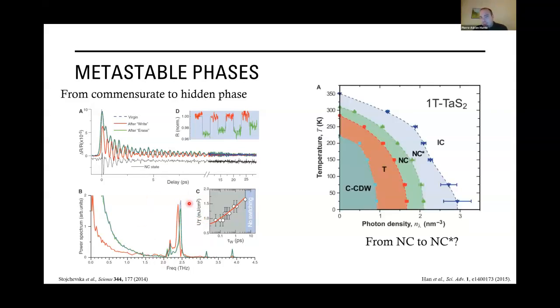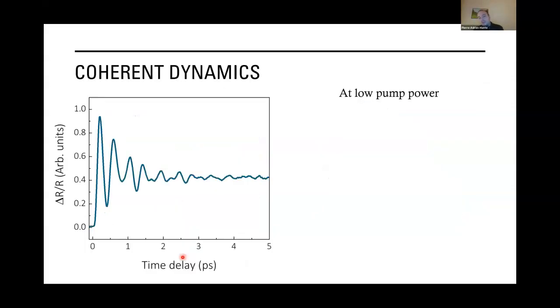So with this in mind, we have been interested in a recent result using electron diffraction, where they predict the existence of a hidden phase that can be driven by photoexcitation from the nearly commensurate phase. So our idea is to try to see if this hidden phase can have a different vibrational signature than the nearly commensurate phase. So we first started to do an experiment at low pump power in order to avoid driving the system into this potential metastable state.